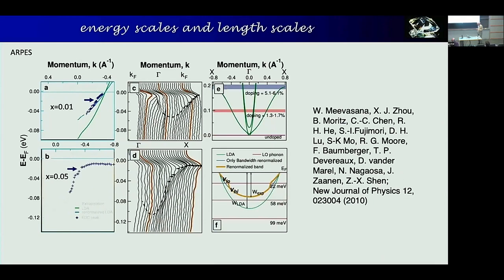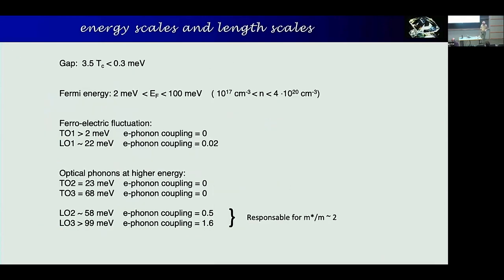Also, it gives you a pretty good fit with ARPES. This is an ARPES paper. And so it gives you the following energy scales. The superconducting gap is smaller than 0.3 milli-electron volt if you believe BCS. The Fermi energy is 2 milli-electron volt at least, or more, up to 100 milli-electron volt, depending on the doping you have. The ferroelectric fluctuation, the TO mode, is 2 milli-electron volt, but that one doesn't couple to your electrons, and the corresponding longitudinal LO mode is at 22 milli-electron volt, so that's way above the Fermi energy.